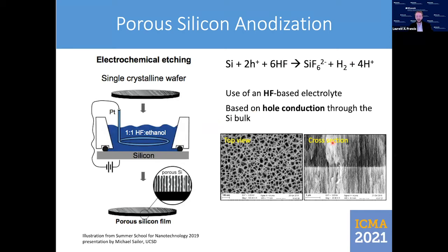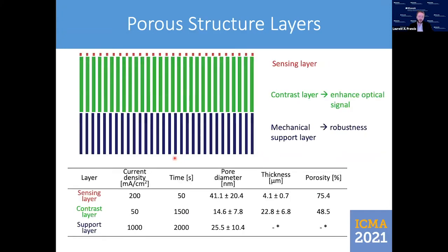Examples of resulting structures are imaged below, with pore size varying in 2 layers with 2 different porosities, as seen in the cross-section here. This is important because our membrane is composed, in fact, of 3 different layers, which are obtained by changing the current density. We have first a sensing layer, which is only a few microns thick. Then we have a contrast layer, which is there to enhance the optical signal. And finally, we have a mechanical support, which is there to enhance the robustness of the membrane and to avoid it cracking or breaking too easily when exposed to the sample.